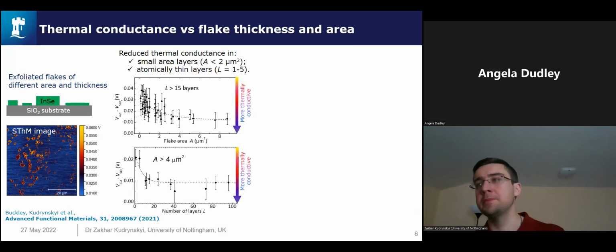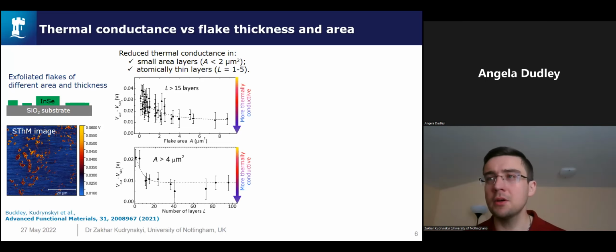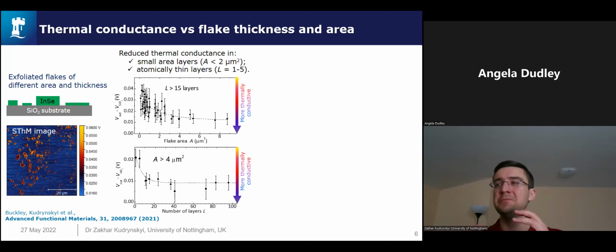To explore the thickness dependence, we examined indium selenide flakes with area of more than 4 square microns and thicknesses ranging from 1 to 100 layers. The choice of relatively large area flakes avoids conflating dependence on thickness with dependence on the area. This study shows that the value of the output voltage is similar for flakes thicker than 10 layers, but doubles in few layer flakes, indicating a reduced thermal conductance in atomically thin layers.